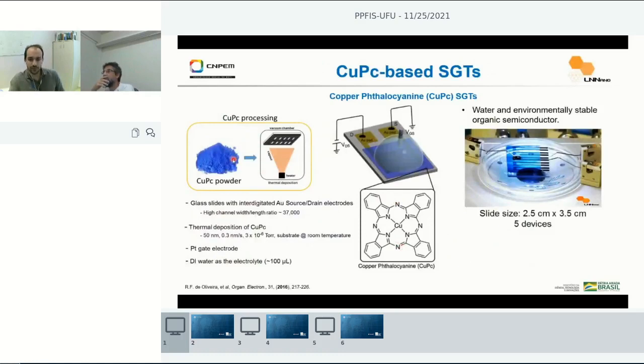So for our semiconductor molecule, we start from the powder. We sublimate the powder by heating it in a vacuum chamber to form a thin film. Here you have the film in blue of our copper phthalocyanine molecule deposited onto interdigitated source and drain electrodes. We place a drop of water on top and immerse the gate electrode. Here's a real picture of our device.